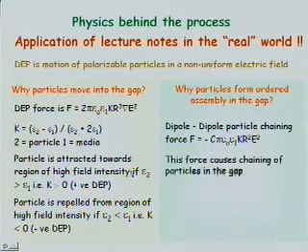This is because of particle chaining. Each particle is basically a polarizable particle. So when you throw this particle into an electric field, let's say you have two particles, when these two particles come close together, their dipoles will like to get aligned in such a way that the total energy is minimized, and the most favorable orientation is the one in which the two dipoles are 180 degrees to each other, and this leads to the formation of chaining like this. Once the chains are formed, these chains can come together and then they can form a two-dimensional crystal.